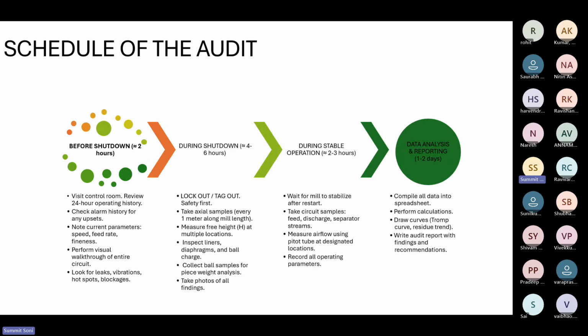Once that data is collected, we start the mill, we stabilize it, and we start taking samples from the belt, from the circuit. Now, these feed samples can be taken either prior to the shutdown of the mill or after the shutdown of the mill as well. I recommend prior to the stoppage of the mill.